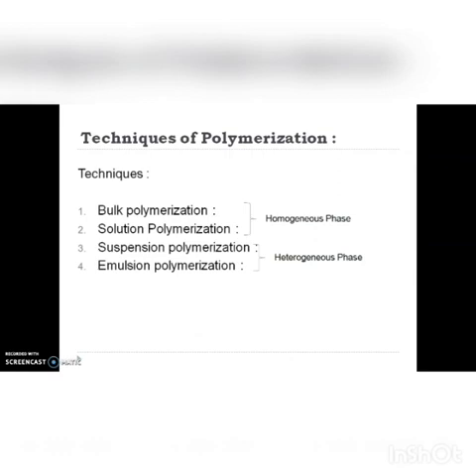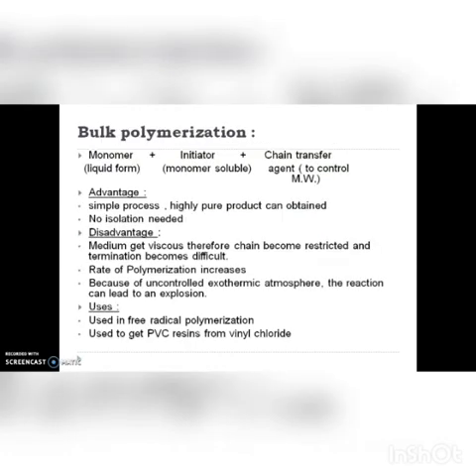There are four techniques by which we can produce polymers. The first is bulk polymerization, which is carried out by adding a monomer-soluble initiator to a pure monomer in liquid state. A chain transfer agent is used to control the molecular weight of the polymer. The mixture is constantly heated to polymerization temperature. Once the reaction starts, heating is stopped as the reaction is exothermic.